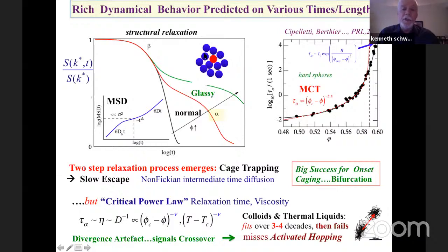And this is associated with some long-lived caging process. And as you increase the density more or lower the temperature more, this plateau becomes more well-defined and the time scale becomes extremely long. So this is a giant success of the mode coupling theory. In my language, I would say it's really been wonderful for predicting the onset of this transient localization and this bifurcation of the relaxation spectrum, the two-step relaxation. It also predicts many other things I don't have time to talk about.